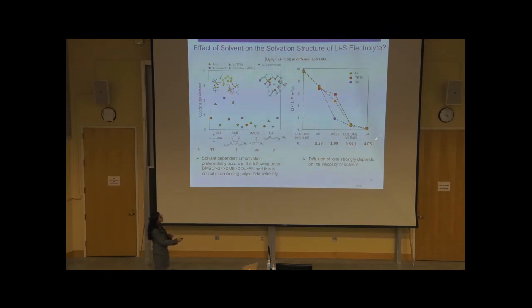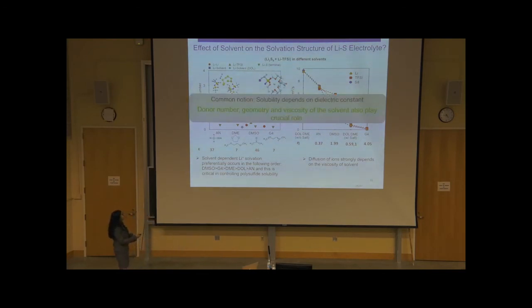And for tetraglyme, we found that diffusion is extremely slow because of the very high viscosity of tetraglyme. So basically, when we are trying to control the solubility or the diffusivity of ions in the solution, along with the dielectric constant, we need to consider the donor number, the geometry of the solvent molecule, as well as the viscosity, which plays an important role in determining the mobility of ions in the solution.